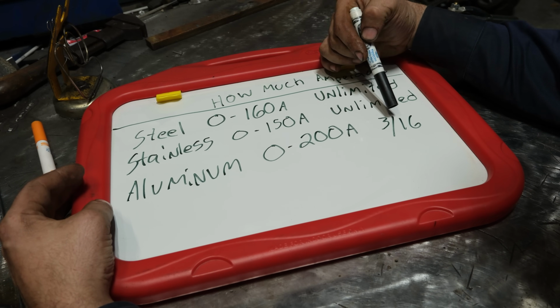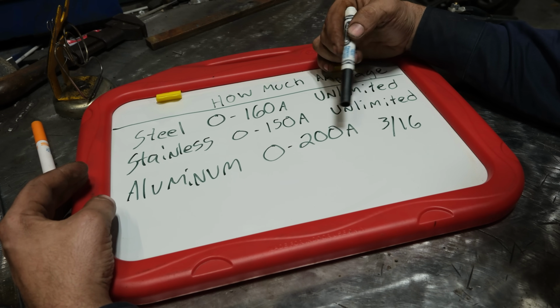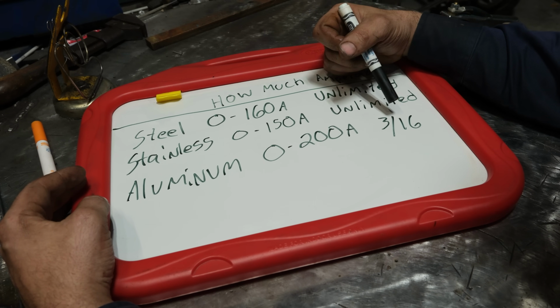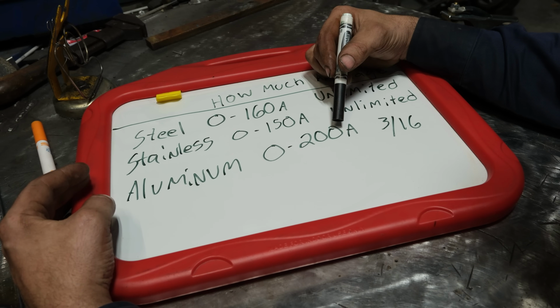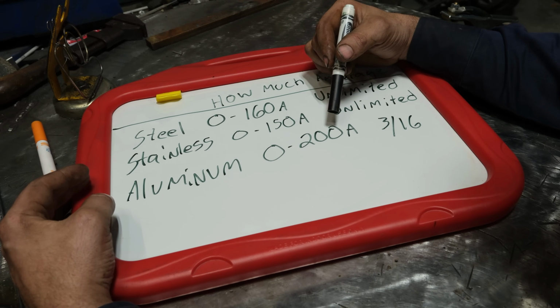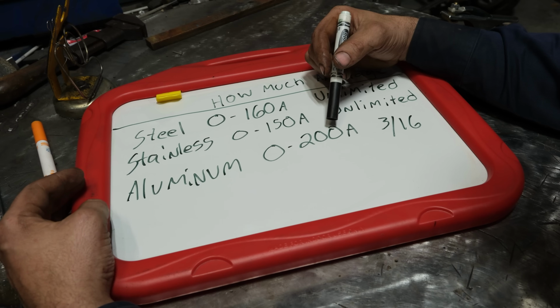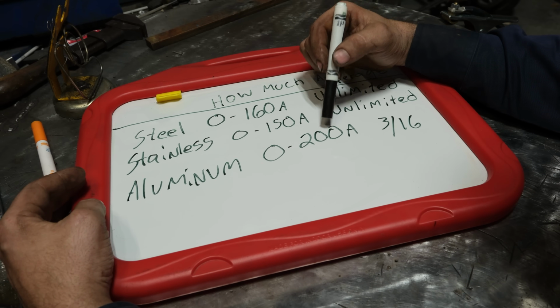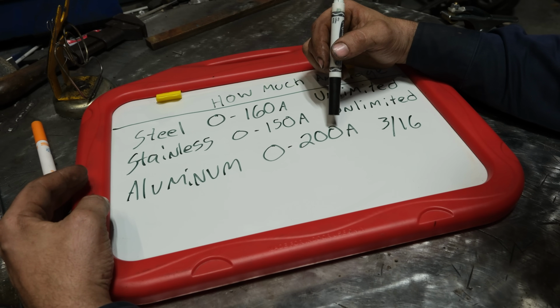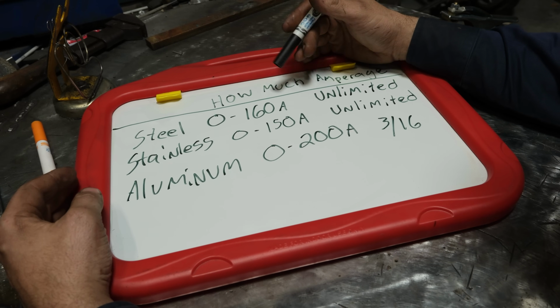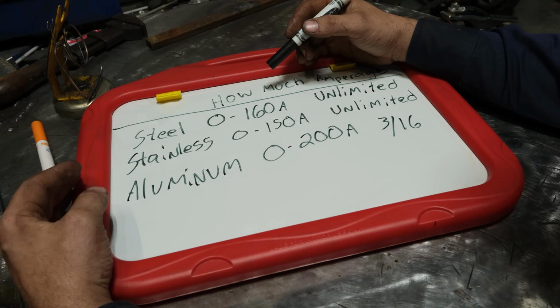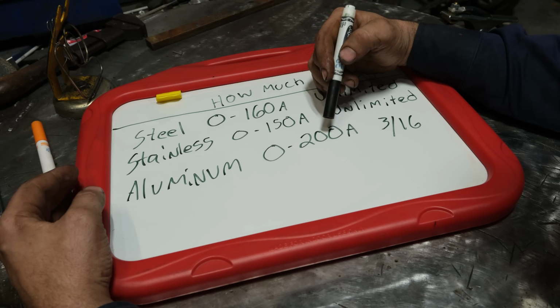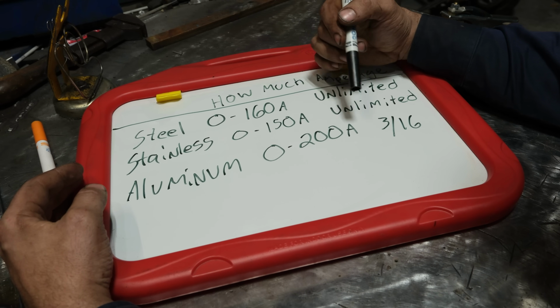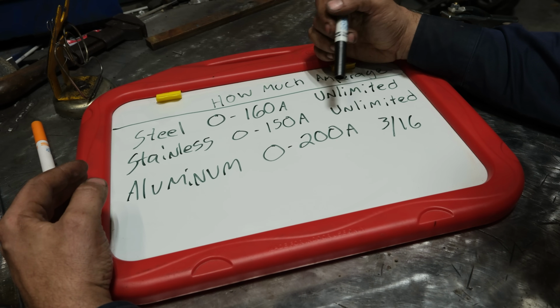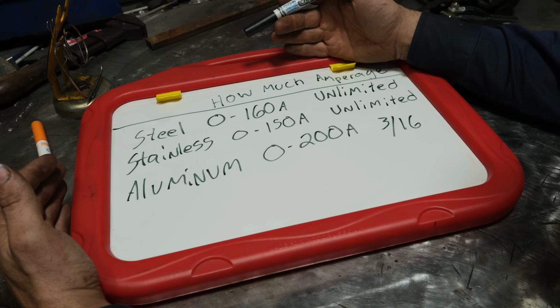And by the way, 200 amps will only allow you to weld about 3/16 thick aluminum. That's not very thick. I have personally used 200 amps full pedal on 1/8 inch aluminum, depending on the joint that I'm welding and the filler rod size. So it's no joke. Do not skimp on amperage with aluminum. A lot of people see these big 300-400 amp TIG welders and are like, why on earth would you need that? It's because of aluminum. Having that much amperage allows you to weld 1/4 inch thick aluminum with no preheat. Now, that is always an option.